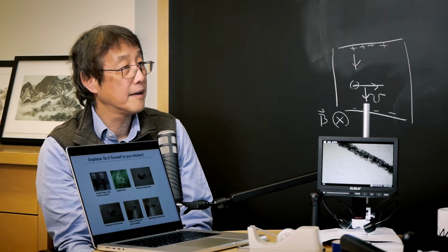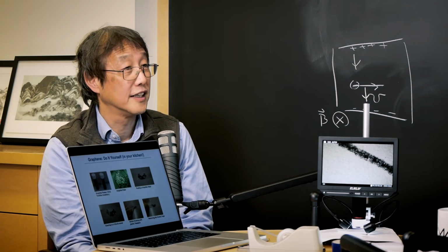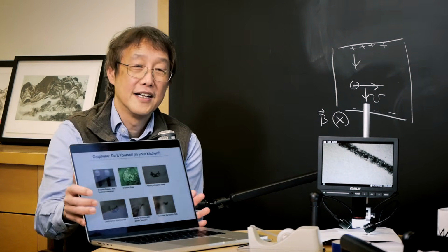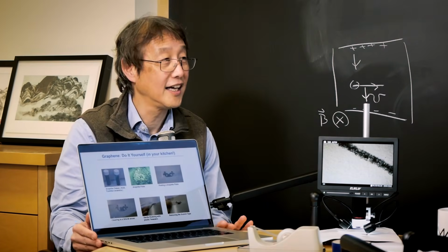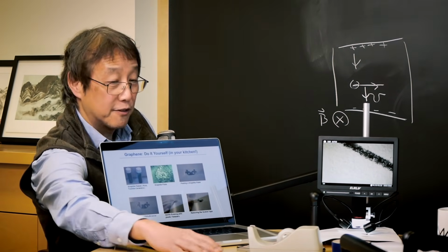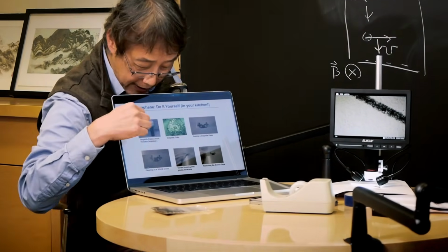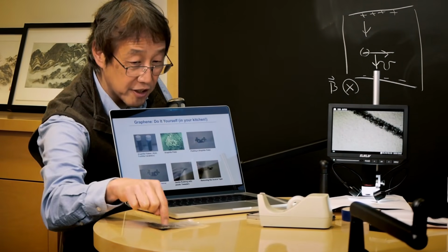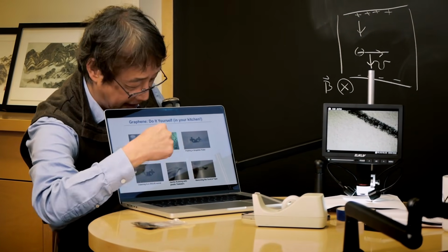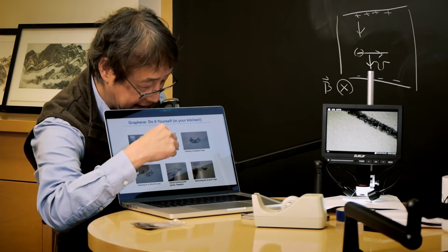And there are also always urban legends that this only works well with Scotch tape and not other brands. No, I think later if you see my lab, there are a few different versions that you will see. So this is a slide that shows how to prepare the sample. You start from the graphite. You have the Scotch tapes, right? You crush this graphite onto the Scotch tapes, looks like this, right? And then put the Scotch tape onto the silicon chip, and you have to rub it.